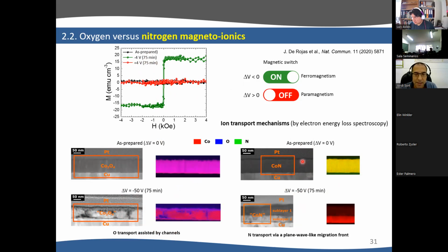So the as prepared sample is homogeneous. You can see here the platinum from the top contact to prepare the lamella, the cobalt nitride and the copper. We apply -50 volt, we have the copper, we have the platinum, but here inside cobalt nitride there are two layers, and the upper one is richer in cobalt and contains less nitrogen. So this might be interesting for devices because you apply voltage, you have a bilayer.